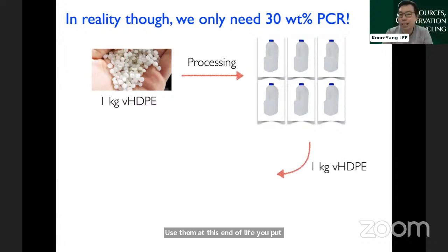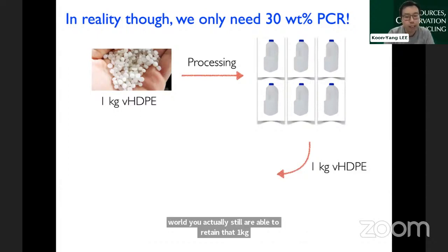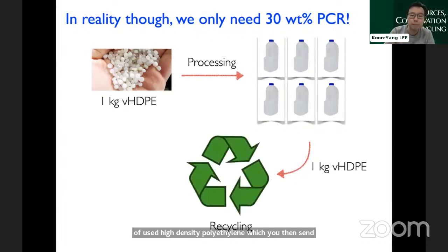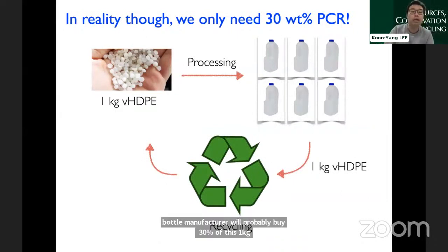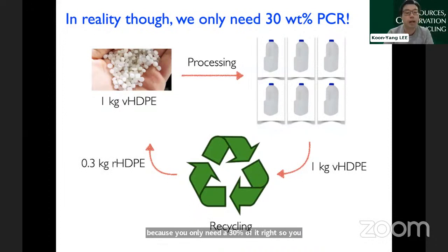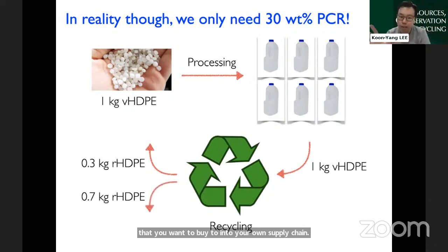Now, assuming again, in a relatively ideal world, you still are able to retain that 1 kilogram of used high-density polyethylene, which you then send back to a recycler. Your recycler would probably send, or you as the milk bottle manufacturer will probably buy, 30% of this 1 kilogram because you only need 30% of it, right? So you will have 30% of that recycled high-density polyethylene to buy into your own supply chain. The other 70%, at the moment, let's assume goes to another industry, but our focus here is on that 0.3 kilograms of recycled polyethylene.